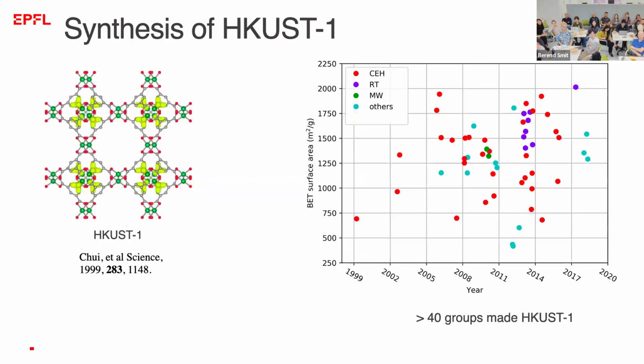So we started simple, and that is we looked at this HKUST-1, and that's a metal organic framework which you can easily synthesize. Even we could do it. But the interesting thing is, this is all the synthesis that is reported in the literature, and they measure the surface area, and the color coding is different experimental techniques. And what you see is, depending on who made it and which experimental technique, the surface area is very different.